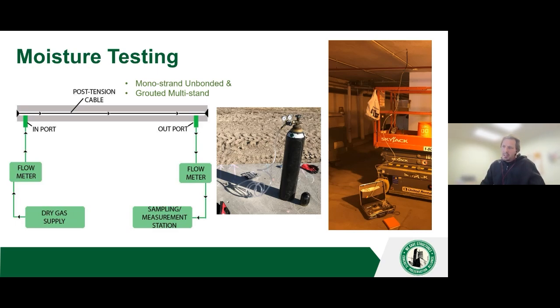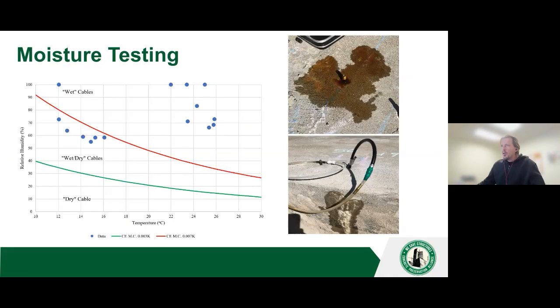So we typically use a dry gas. Nitrogen is often what we're going to use. And we use an inlet port and an outlet port, right? And we just pump that dry gas through the tendon with a moisture meter on the other end. If there's water ponding inside of that, in the bottom of that drape, you're going to see your moisture test go up quite a bit, right?